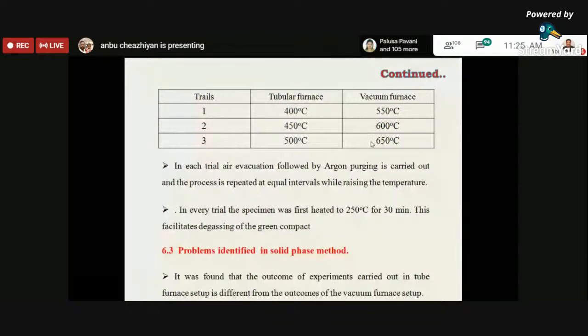The reason is we had not obtained the compact properly. So for that purpose, we increased the temperature to 550 degrees centigrade. Before each trial, air evacuation followed by argon purging is carried out, and the process is repeated at equal intervals of time.